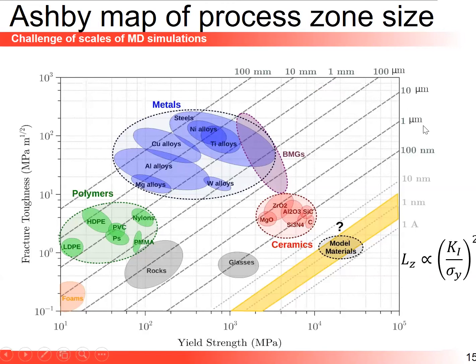So, orders of magnitude too large for what we can achieve for most materials with atomistic potentials, classical molecular dynamics. So what we did originally to find this brittle mechanism was to come up with model materials that are extremely brittle, so that we lower their scale to domain sizes that we can very quickly solve on our computers to develop this insight. And now actually we're moving back up to more traditional potentials, looking at ceramics, and we are able to see this transition at a higher cost, but we can do this.